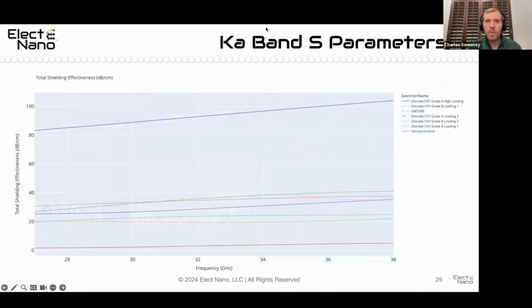And so when we compare our materials to industry standard EMI absorbers, we can match performance at very low carbon nanotube levels, fractions of a percent up to a few percentage points of carbon nanotubes, compared to something that has like 30% silver or ferrites that have been added into it. And then if we supercharge the amount of nanotubes that we put into it, with a higher loading level, we're just blowing it out of the water, 80 to 100 decibels per centimeter in terms of absorption, which is log scaled. So that is a lot of signal quenching.